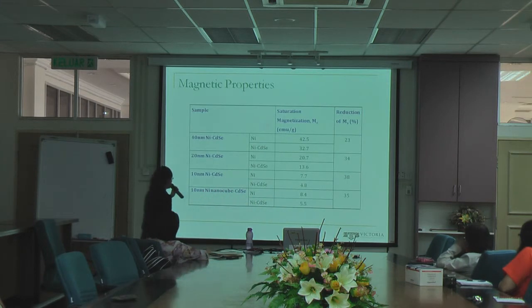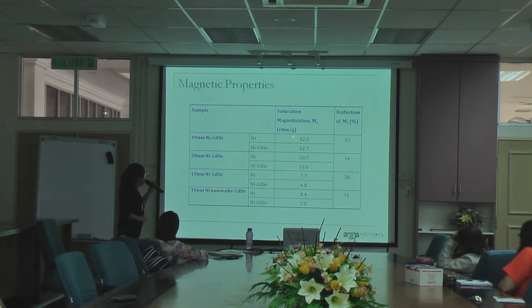So two things that we are seeing here, which is quite general: as we decrease the particle size of nickel itself, the magnetization value of nickel also decreases. And for all cases, once we have added on the cadmium selenide coating, the overall magnetization also decreases, and the decrease is much higher for smaller size nickel.